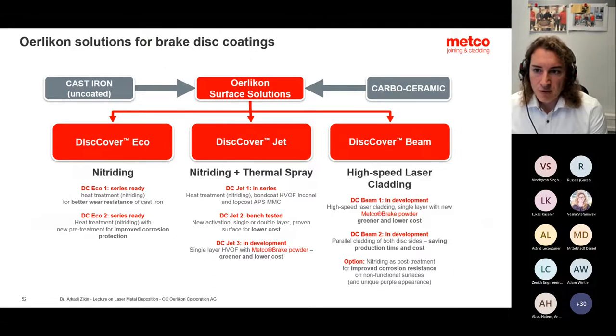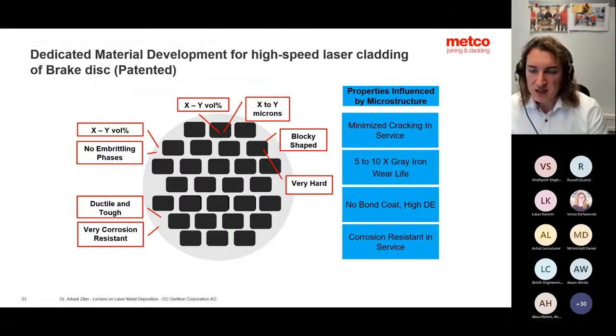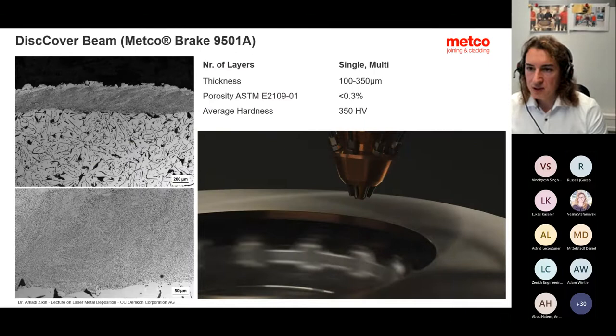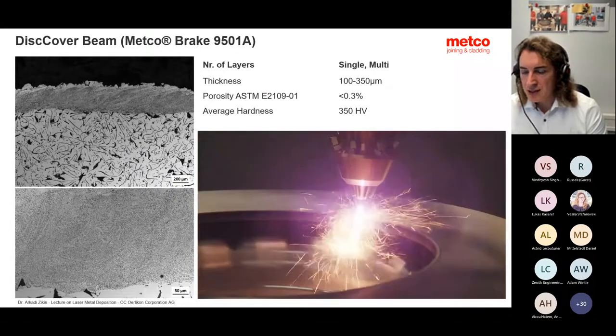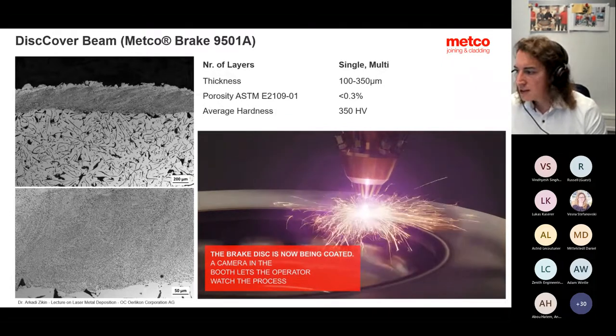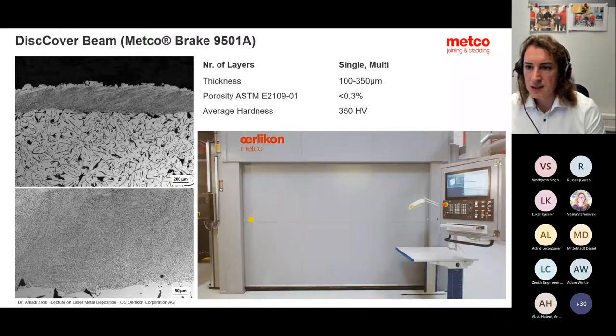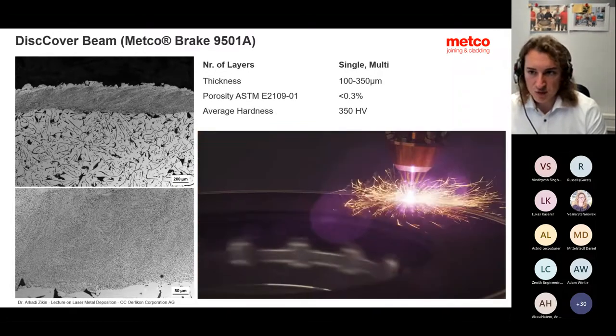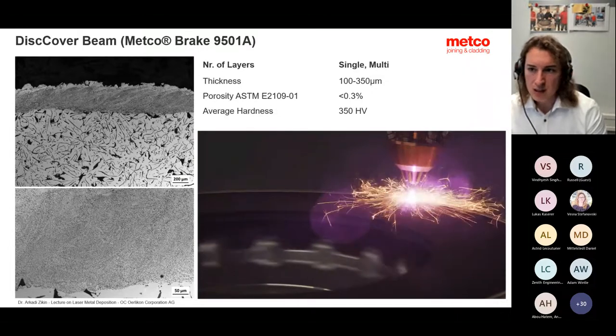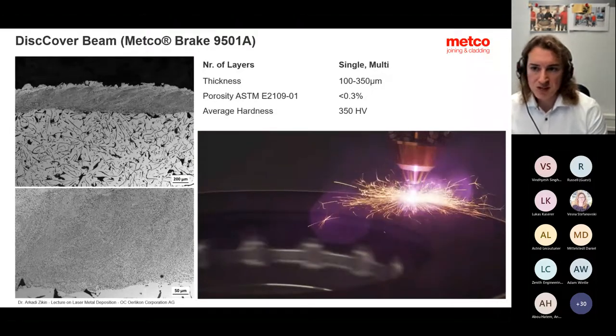Another example, as the world is now getting more and more attention to brake discs, there is an early solution for brake discs where, in a similar way, an iron-based material was designed to meet the requirements from the automotive environment in terms of wear resistance, corrosion resistance, and also in terms of being deposited directly on gray cast iron using a high-speed approach, having very good surface quality, very good properties, no cracks, and at the same time can compete with typical carbide materials or double layer solutions, which were also introduced in similar presentations before.